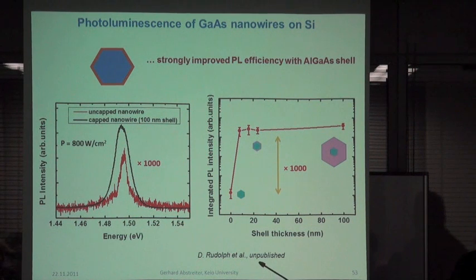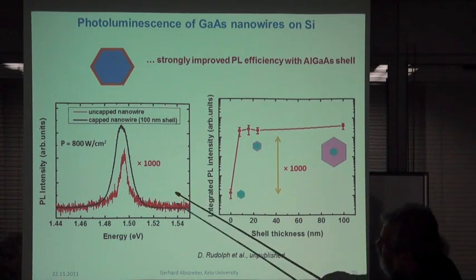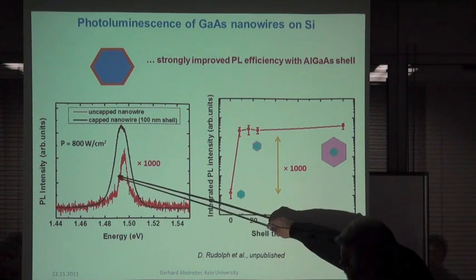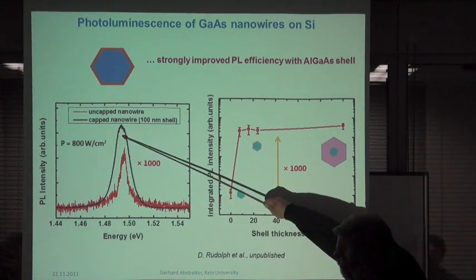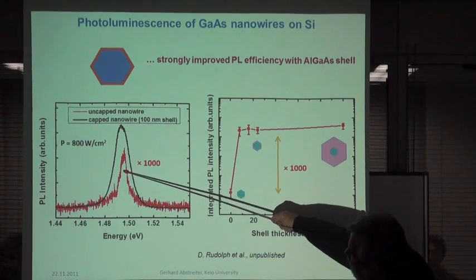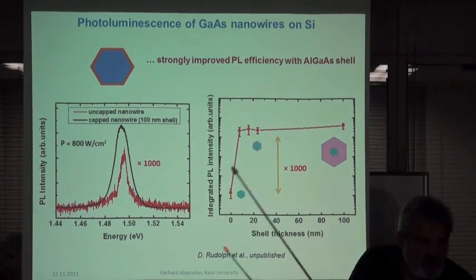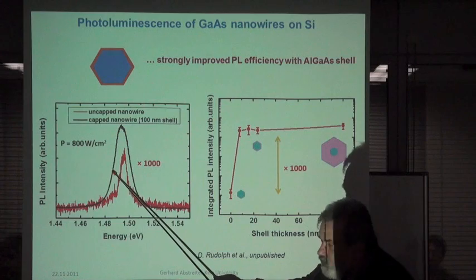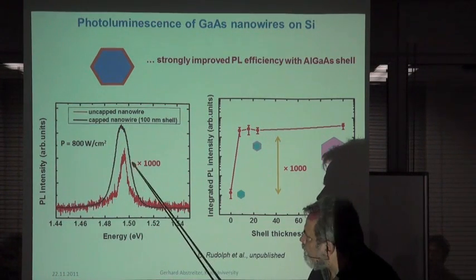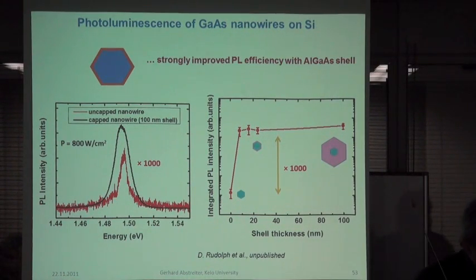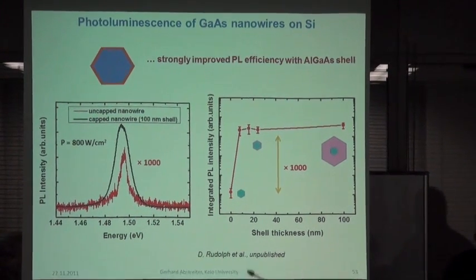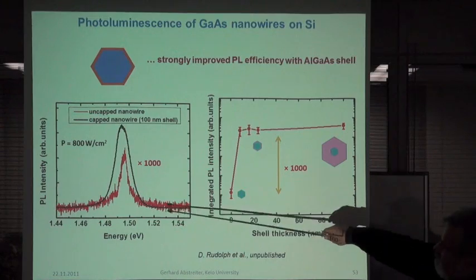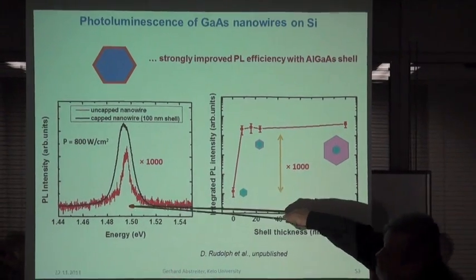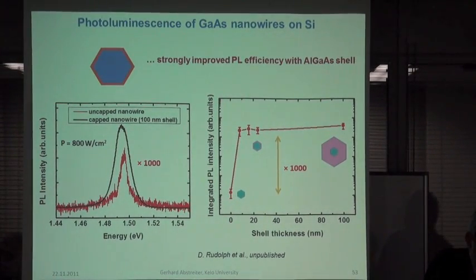Is it broader? Pardon? Why is the black curve broader? This is the example which I show here. The width depends on the structure of the initial part, and this was a different wafer where we later found that this wire has a higher density of twin dislocations, which gives you altogether a broader line. But despite this, we got a strong increase in the intensity.